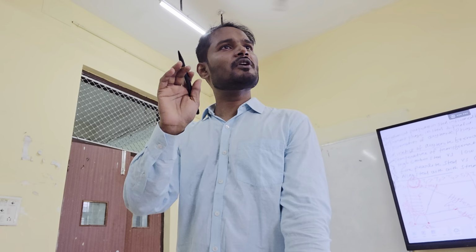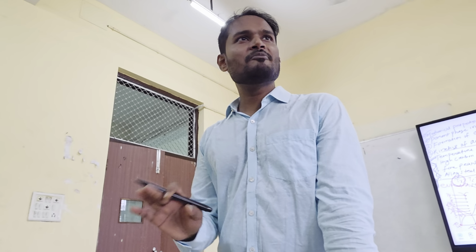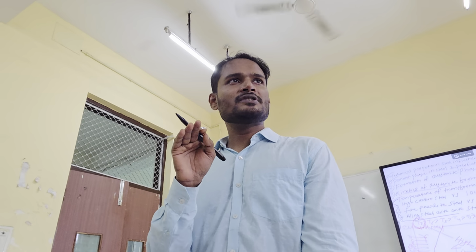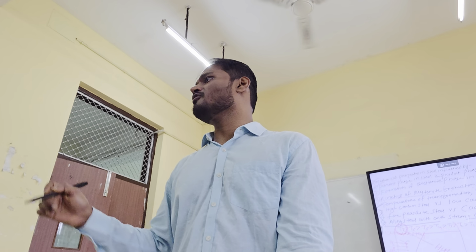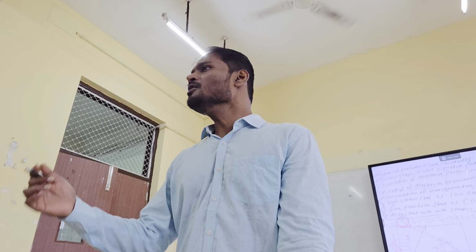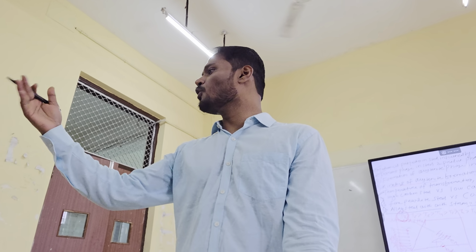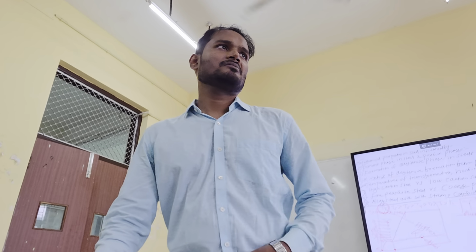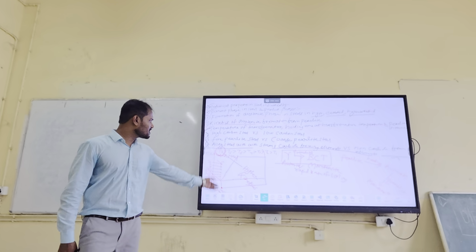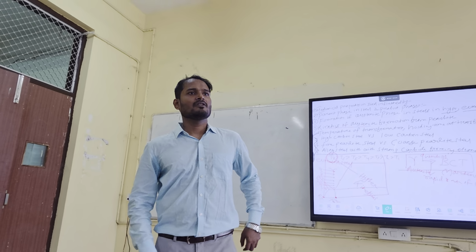So how am I correlating, you understood? Right? You can write this in the exam also, in the end semester, if the question comes. Again I am saying, higher the austenitizing temperature or higher the transformation temperature, higher the kinetics of austenite formation. Why? Because the nucleation rate is high and the growth rate is also high. Similarly, higher the holding time at the austenitizing temperature, higher the kinetics of the austenite transformation. Okay? If you remember this diagram, you can write everything. There is no confusion. Just remember this.